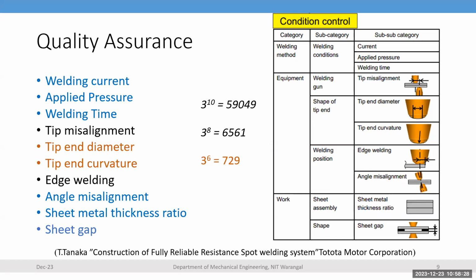Then the shape of the tip end. The tip end may change shape, which changes the resistance, so variation in heat generation also takes place. Then welding positions. If you want to weld near the end, you must see the minimum distance you leave before the end of the component. That is also important. Then angle misalignment. Sometimes you weld at a particular angle, and you have to check whether the angle alignment is there or not.